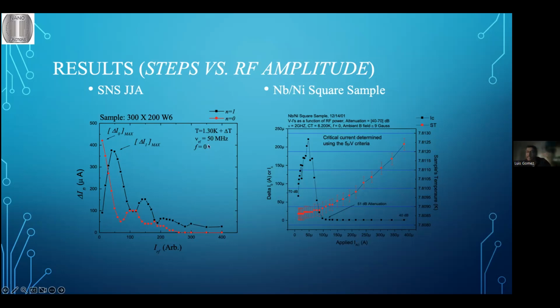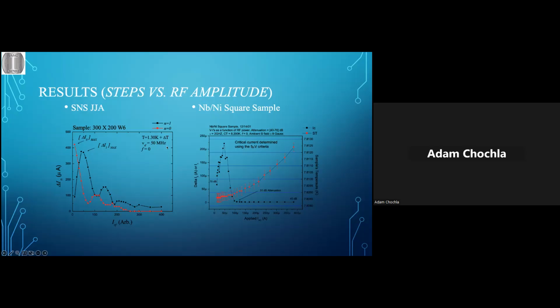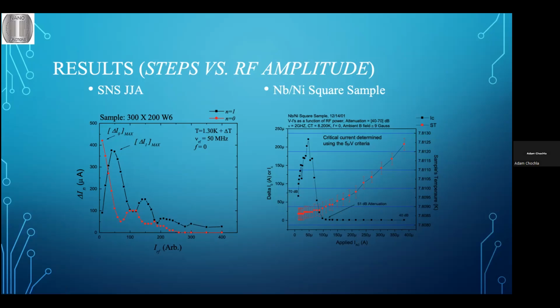So I changed it. In this case the frequency is much lower, because the product of the critical current multiplied by the resistance is much lower. I don't have the number here, but in, for instance, classical microelectronics or conventional junctions, the capacitance plays an important role. But if we don't see any significant changes in these characteristics, this means that the key role is played by the superconductivity phenomena in this case.